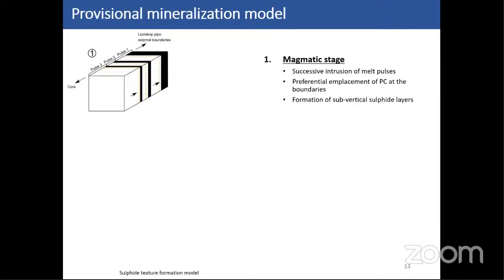So based exclusively on the textures, it's possible to come up with a provisional mineralization model, as I consider it. First a magmatic stage, which is characterized by the successive intrusion of different melt pulses. And as you can see, with alternance of banded carbonatite and phosphorite, as well as the fact that phosphorite is preferentially in place along the boundaries with the host rock, we have a progressive decrease in iron oxide, phosphate, and silicate contents from early stages to later ones.